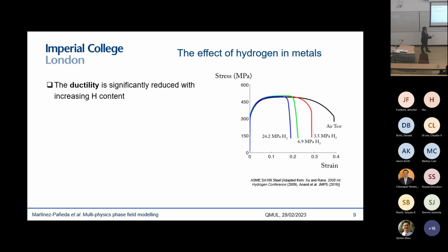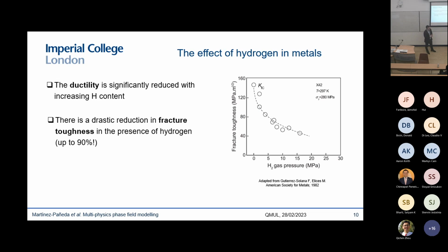You can see here, this is a stress strain curve, so in the actual tensile test, and you can see that if I introduce hydrogen into my samples, by, for example, exposing them to hydrogen gas, then you get a very significant reduction in the failure strength. Another effect is how hydrogen brings down dramatically the fracture resistance. So you can see here fracture toughness versus hydrogen content, and you can see that a material that has a fracture toughness of 150 megapascals per meter will fail well below 40 megapascals per meter in the presence of hydrogen. And this is for a low strength steel.